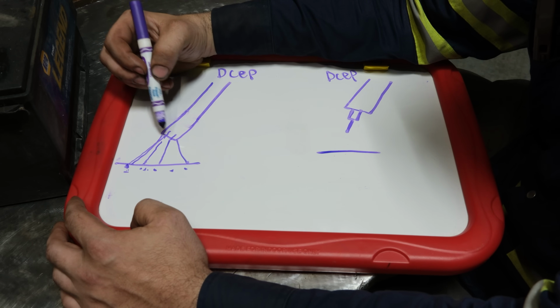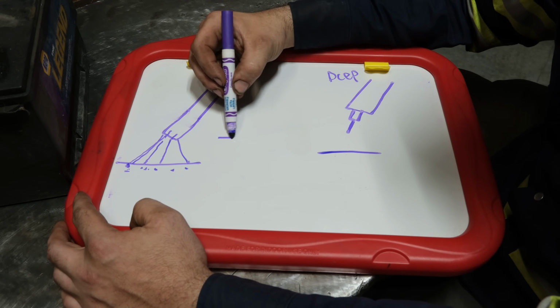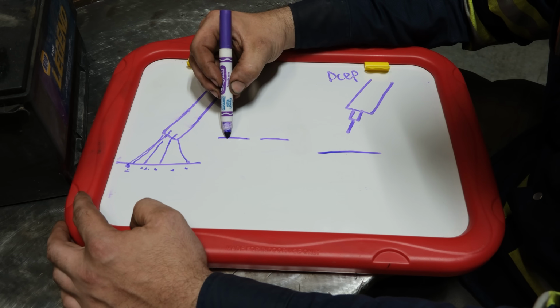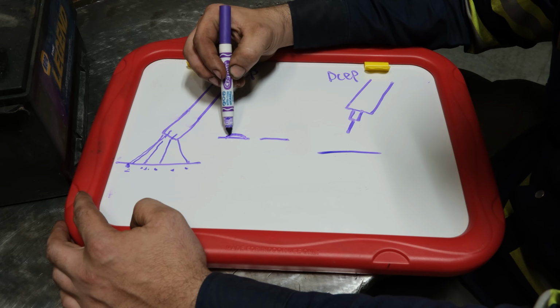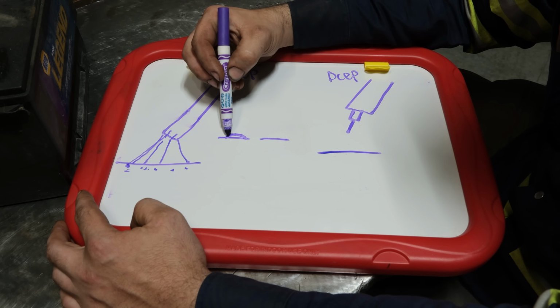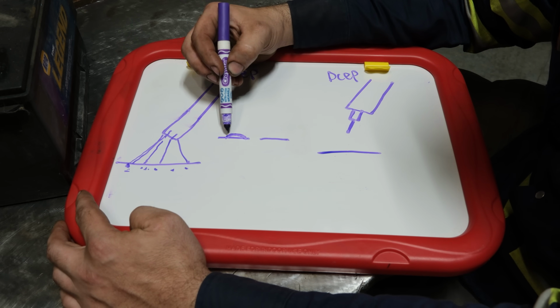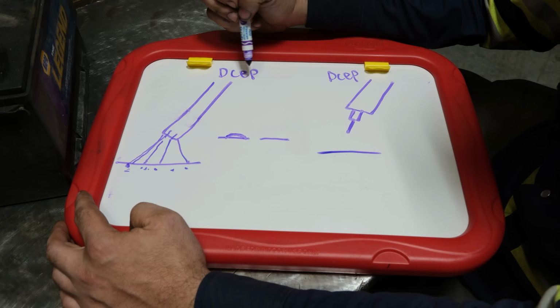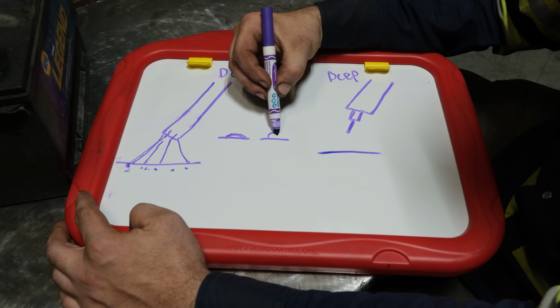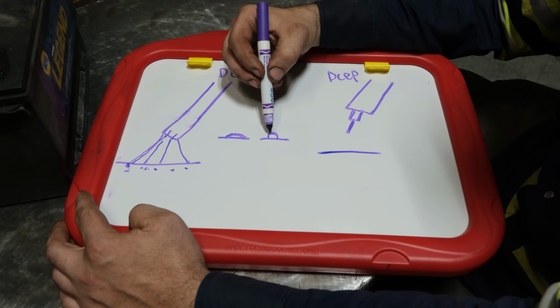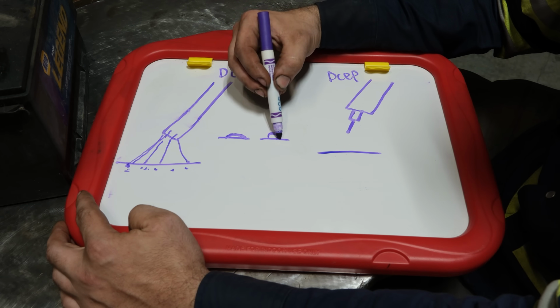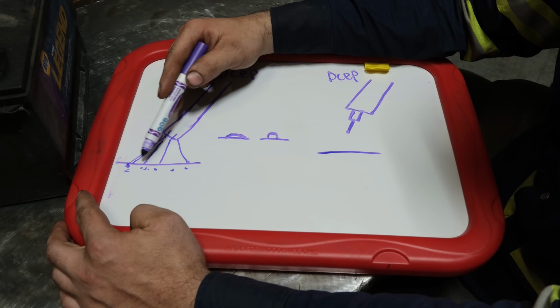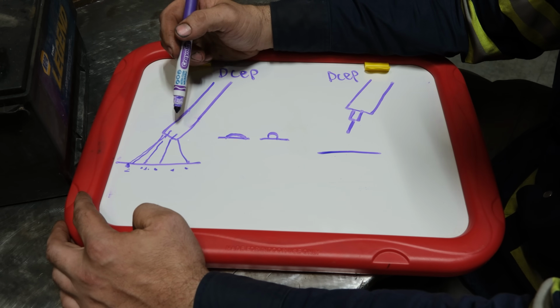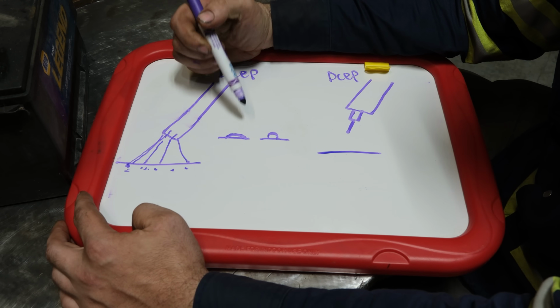Typically, no matter how much amperage you run, the profile, so I'll draw two welds here. This would be like your typical 7018 weld. It's somewhat not ropey, but it's got a concaveness to it and some reinforcement. Well, if you were to weld on electrode negative, your weld bead would tend to rope up significantly due to the fact that your arc will actually be narrower. And for the most part, it's undesirable.